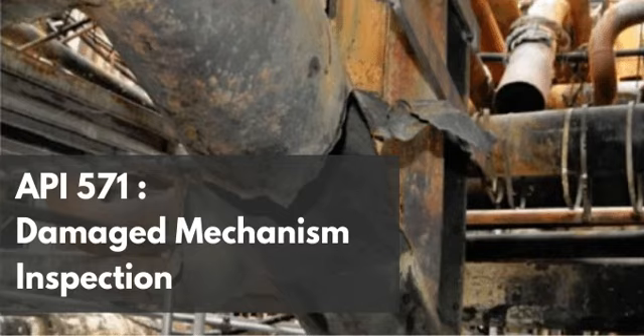If we connect this to the bigger picture, the code provides a crucial insight here. The effect on toughness is actually not pronounced at the operating temperature. Wait, really? The brittleness doesn't exist when it's hot? It's not that the microstructural damage disappears, but rather that the heat actively masks the symptom. Oh. When the metal is sitting at 800 degrees Fahrenheit, there is so much ambient thermal energy in the system that the atoms still have enough mobility to physically slide past those alpha prime roadblocks we talked about earlier.